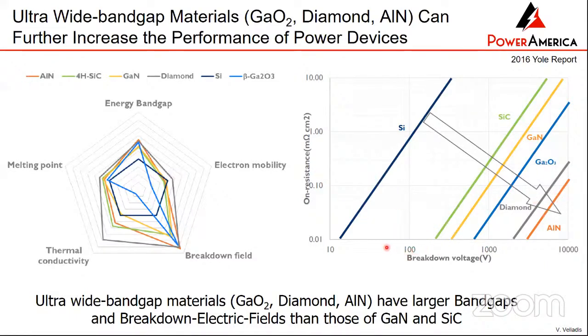This graph shows the breakdown voltage, the amount of voltage that the device can handle, and its equivalent resistance. So if you want to make a device that does 1,000 volts using silicon carbide, your resistance will be right here. If you use gallium nitride for the same 1,000 volt device, you can make that device with low resistance. If you go to diamond, it's lower. And then of course, aluminum nitride is even lower, and silicon of course is very, very high.